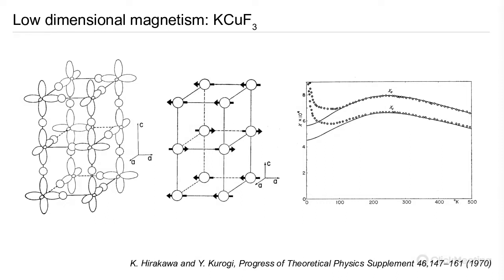Nonetheless, this does actually order at low temperature. The magnetic structure was determined, and it also has this accompanying orbital order, where what's drawn here is the partially occupied d x² minus y² orbital of copper in the system.